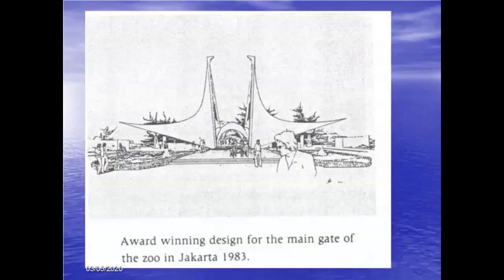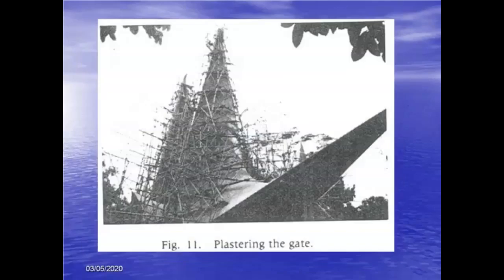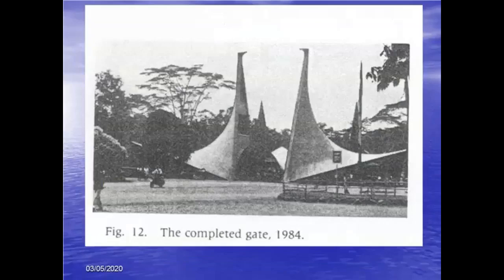An example structure in Indonesia needed protection with an opening. Using pure concrete would increase thickness significantly. Instead, skeletal rods were placed and steel wire mesh was laid over them. The structure was completed with ferrocement, resulting in about 30 to 40% reduction in dead weight of the structure, with an elegant higher-quality finish.